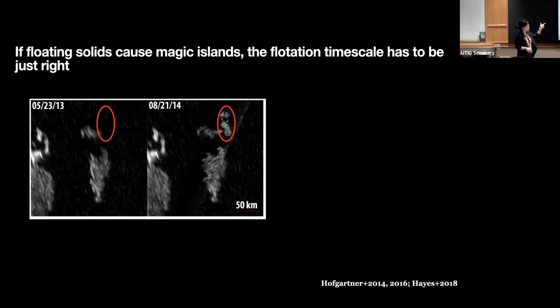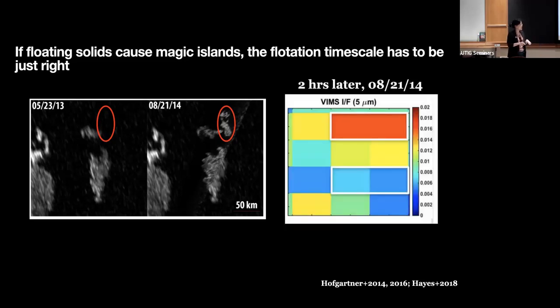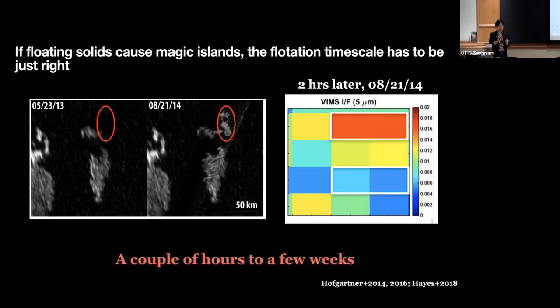And basically 2 hours after the observation of the magic island, they also take another data set, which is through the visual and infrared mapping spectrometer on Titan. And they see this red feature on there, which is probably also the lake, depending on how much you trust this data. But anyways, we think based on all the observations we have, these features have to last. If you float on it, it can't be just seconds. It has to be longer than that, a couple hours or a few weeks, but not so long. Okay, it can't be too long or too short. So this timing is important.